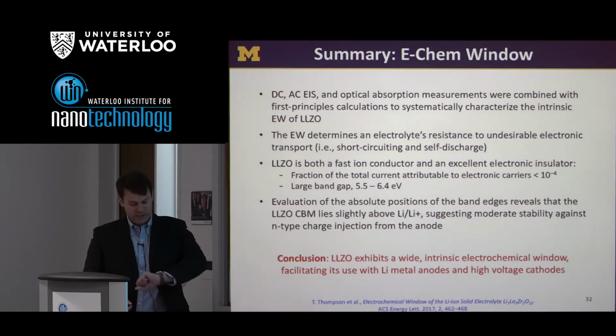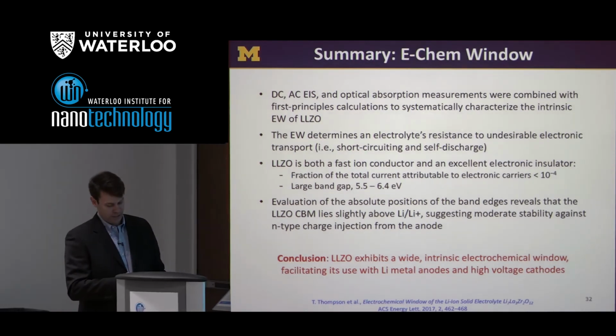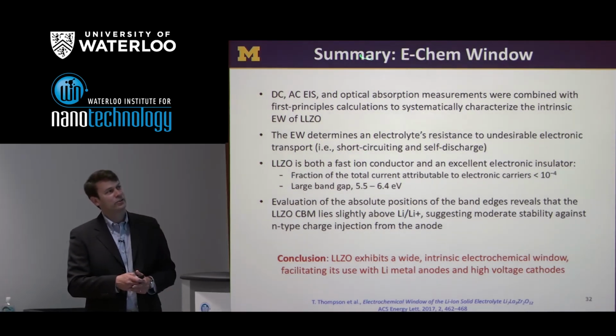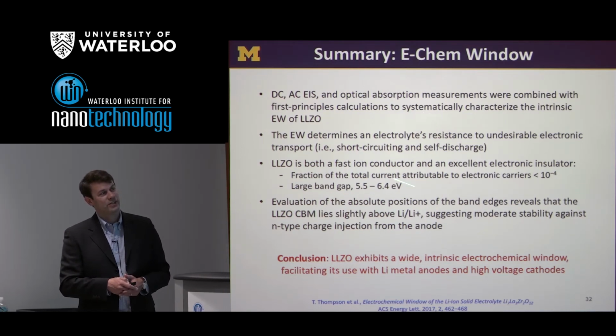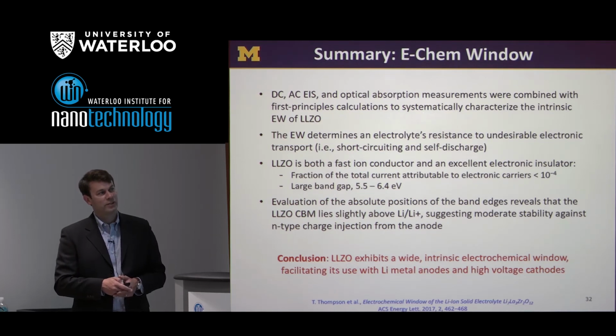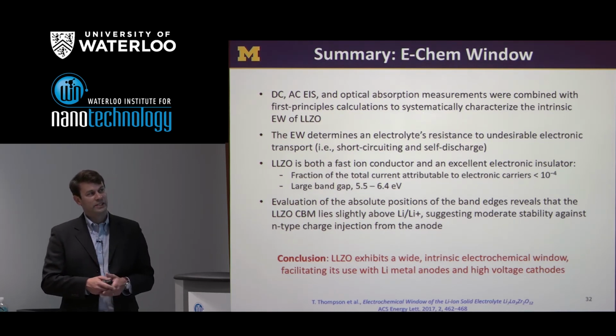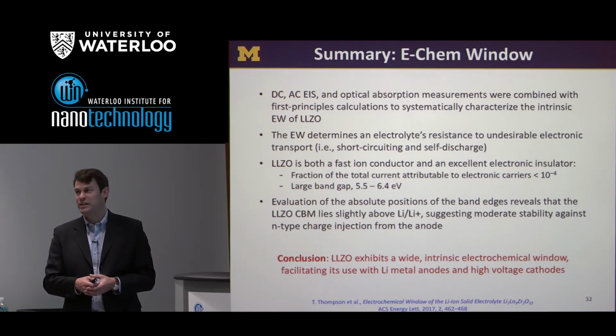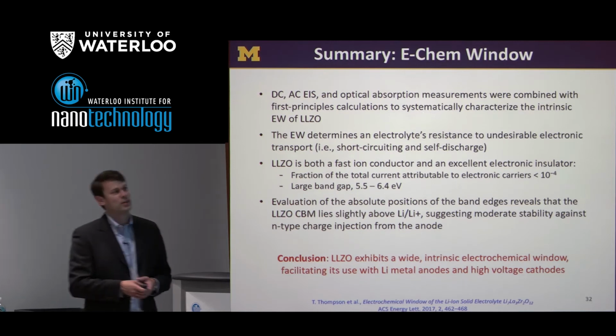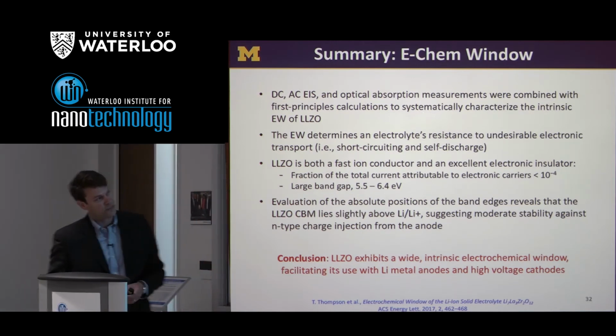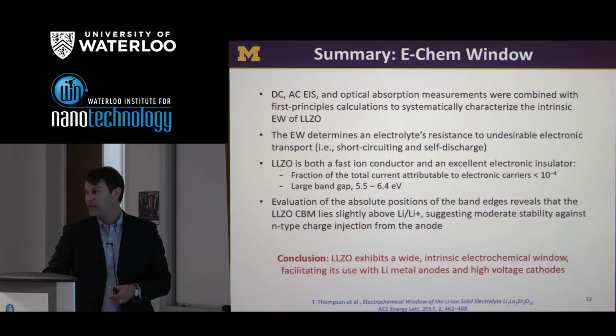So to summarize this portion of the talk, here we are interested in calculating the electrochemical window. What we've looked at is the band gap of LLZO. We think that it's a nice wide band gap material. It's also an excellent electronic insulator. And the CBM looks to lie slightly above the lithium plus level. So we'd like to extend this electrochemical window idea to other solid electrolytes to see how others perform with respect to stability of, say, a lithium metal anode.